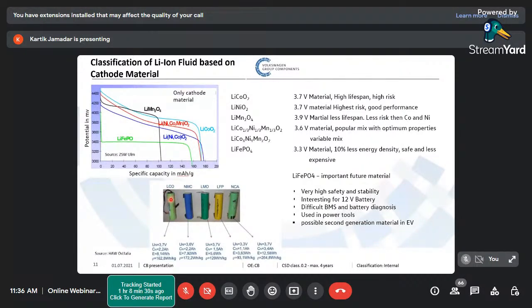LCO will be very high cost because of the high cobalt content. NMC has good properties in terms of energy density, but because of the high nickel content, it is a little bit unsafe. NCA would be the highest energy density but more unsafe. LFP has the lowest energy density among all, at the same time very safe. LMO has a very high voltage, but it has a problem that it does not have that high cycle efficiency. So one has to choose which is the best one for us. They are all available in the market. And this is a discharge curve which you see with time. When we are talking about the LFP material, we should see that the LFP material has a very flat curve.